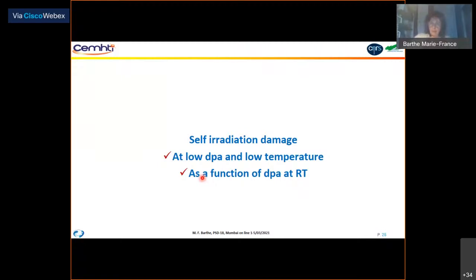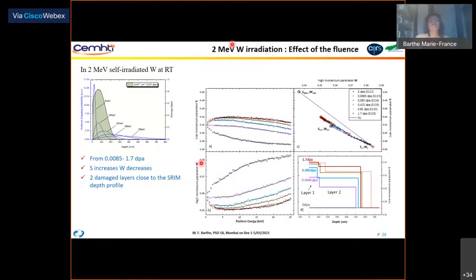So now, if we look at what happens when we increase the dpa level, this time the samples have been irradiated with 2 MeV tungsten and at different fluences corresponding to a dpa level from 0.0085 to 1.7 dpa, and we can see that S increases with the dpa level and W decreases, and we fit this data using VEPFIT, and we obtain 2 different damage layers. The first one, where we can find the highest S, corresponds to a depth of about 100 to 150 nanometer, as it was for the SRIM depth profiles.